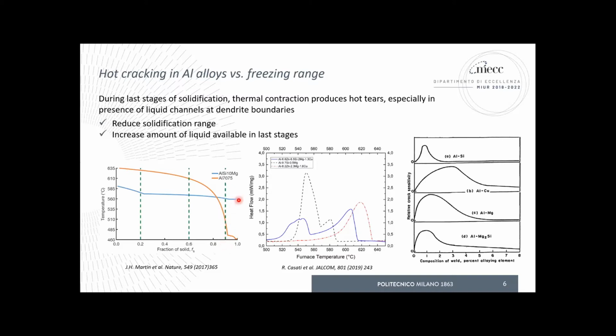What can we do in order to smooth down, to produce a flat curve in the last stage of solidification? We can play with the chemistry, of course, for instance, inducing a large amount of eutectic constituent in the alloys. We can modify somehow the composition. You can see it from the plot here on the right, which is a very old plot. Actually, I couldn't track back the reference, so I'm sorry for the authors that are not mentioned for this plot. But it shows that it comes from welding again.